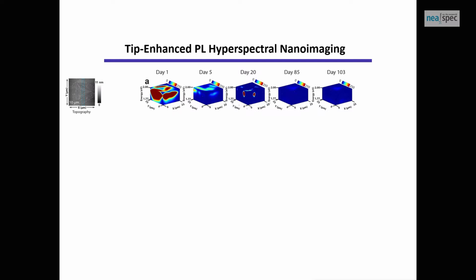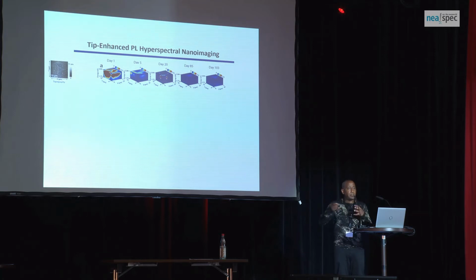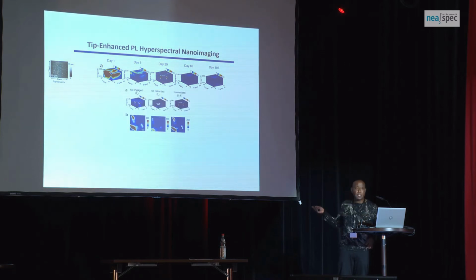so we started by taking a hyperspectral image at each pixel on this sample and form this 3D cube of the PL emission. And so this XY plane is the sample plane, and the Z-axis is the energy axis. This is similar to hyperspectral in nano-FTIR, those of you who work in nano-FTIR. And so we follow this cube over time, so how it changes over time. And as you can see, it's quite hard to understand. And the cube changes, so the way to understand this is, this is how we do the measurement.